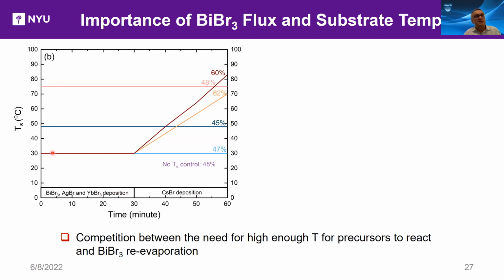So it turns out that if you keep the substrate temperature at 30 degrees, 50 degrees, or around 75 degrees, you get 47%, 45%, 48% photoluminescence quantum yield. So it doesn't change very much, and it's definitely not at the high level that I was showing you. If, on the other hand, you ramp the temperature from 30 degrees to some upper temperature, then you get to 60% and 62%. Note that you're passing these temperatures along the way in the ramp. So the ramp is doing something. It's not the temperature that you end up in.